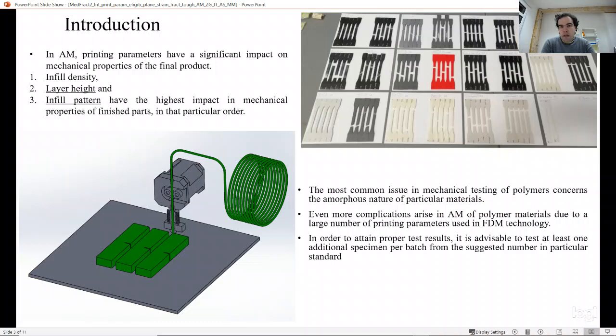And not only this problem, but concerning additive manufacturing, you also must add printing parameters as a significant influence on mechanical properties of final products. From our previous research and literature findings, we see that infill density, layer height, and infill pattern have high impact on mechanical properties in this particular order. First, infill density has the highest influence, then layer height, and next is infill pattern.